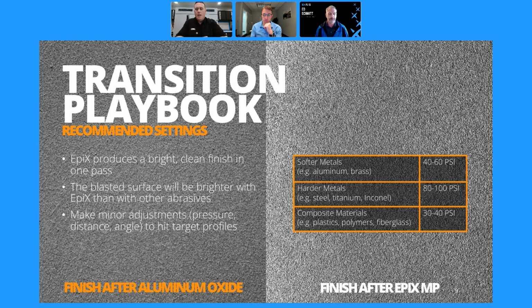Yeah, we were able to take a couple panels, a couple blasts with aluminum oxide, and then one blasted with garnet sand, and then we had one blasted with EpiX MP. We were able to look under a real high-powered microscope, and we noticed that the aluminum oxide and garnet sand left a little thin barrier of dust within the profile. And on the EpiX MP one, it had a real bright, shiny look to it. And if you put them side by side, you would almost think that the EpiX MP one wasn't blasted. But after looking under the microscope, we noticed that that dust barrier film wasn't there, and you were just getting an ultra clean blast profile.